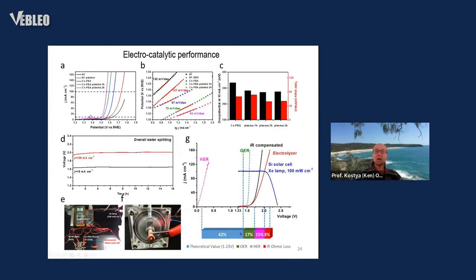But the catalyst started behaving much better than before the plasma treatment, as we can see that the overpotential of the oxygen evolution reaction was significantly reduced, and that the kinetics of the reaction was enhanced, as exemplified by the lower Tafel slopes achievable, and also by the high stability of the catalyst that was able to operate over many hours, even at the relatively high current densities of 100 milliamps per square centimeter.